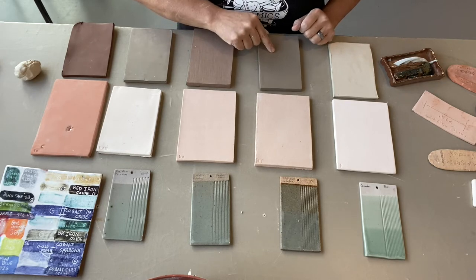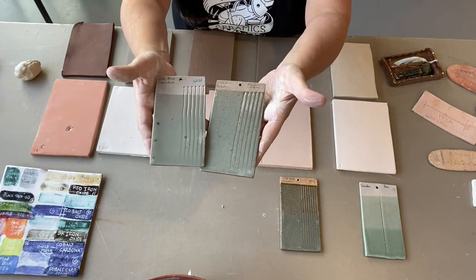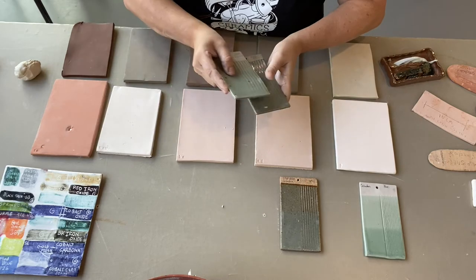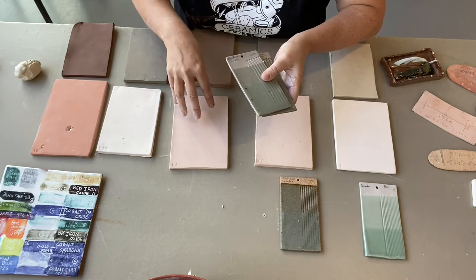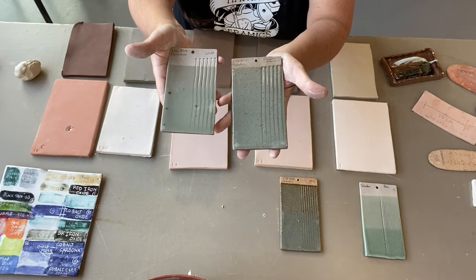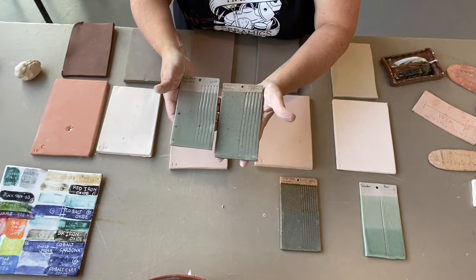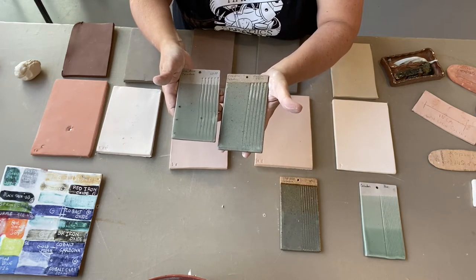We have a body that has something added to it to make it even stronger. If we look at the white and brown stoneware, we can see the celadon glaze that's been applied after the clay was bisqued — that first firing makes it a little bit easier to handle; it's still absorbent, so I can put this in a bucket of liquid glaze and then go into the firing. This celadon looks very different depending on whether it's on the white stoneware or the brown stoneware. Think of it almost like artists deciding how to prep their canvas — the artist or designer wants to consider what is the base color that the glaze is going to react to.